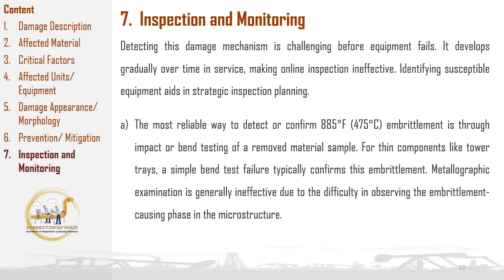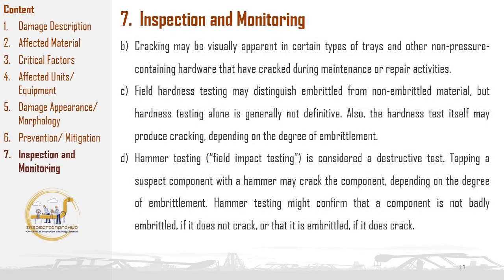Given these limitations, a proactive approach to inspection is crucial. This includes closely monitoring equipment exposed to the critical temperature range 600 to 1000 degrees Fahrenheit and developing targeted inspection strategies. Visual inspection can be effective in certain scenarios, particularly for non-pressure-containing components such as trays and other hardware. Cracking may become visually apparent during maintenance or repair activities, providing a clear indication of embrittlement. Visual inspection, while straightforward, is limited to detecting damage that has already progressed to a visible stage.